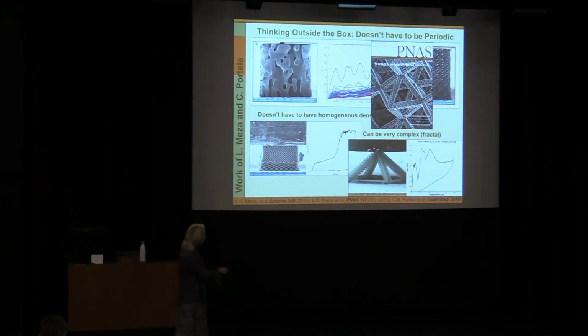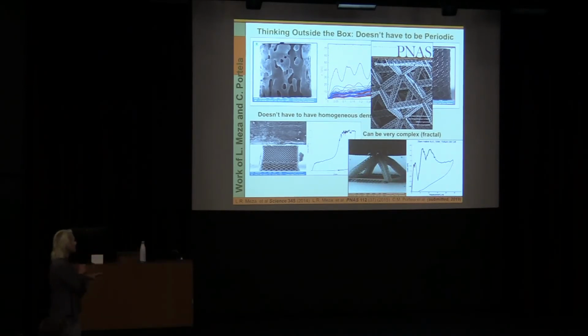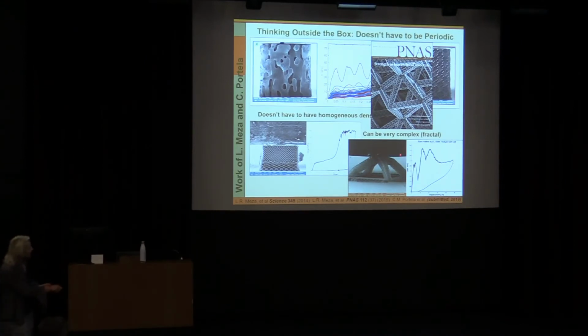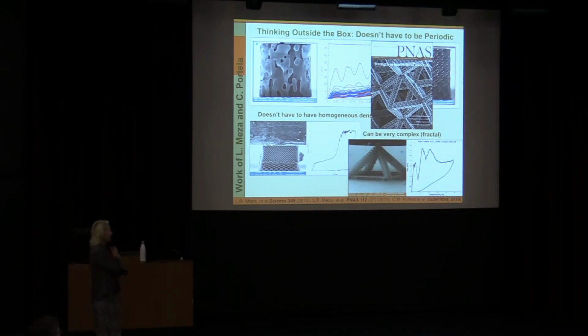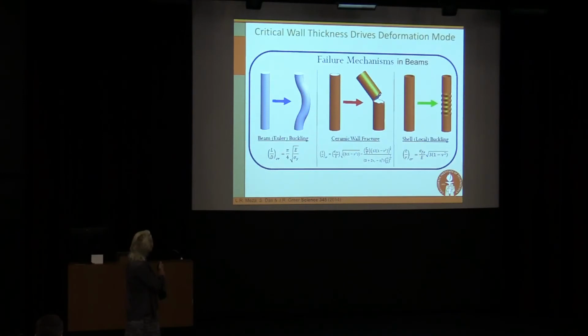Now, look at this very complex shape. So now each beam is a fractal. And so now we have these, it's made out of these self-similar units within each beam. And you can see the kinking here. So we're expecting the failure to occur right in these kink locations as we're compressing it. And it's recovered. So all of these examples are all very brittle, very brittle materials that should instantaneously crack, so they don't. So, well, of course, we wanted to know why this happens.